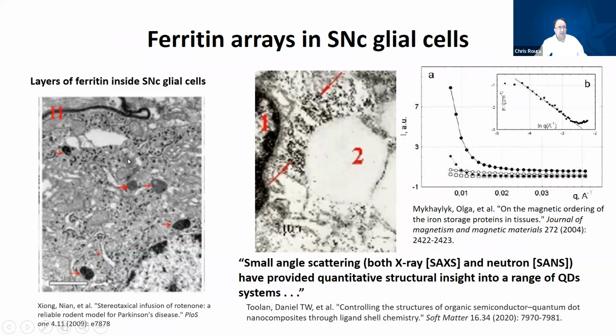This can be seen in this electron microscope photograph of a glial cell from the SNC. The paper does not describe these black dots as being ferritin, but they are very similar in appearance to these black dots in human placental tissue, which was identified to be ferritin. Dr. Mykhaylyk was testing the human placental tissue for increased magnetic ordering using small angle neutron scattering. And she did find that there was a substantial increase in this magnetic ordering compared to the ferritin after it had been removed from the tissue and tested separately.